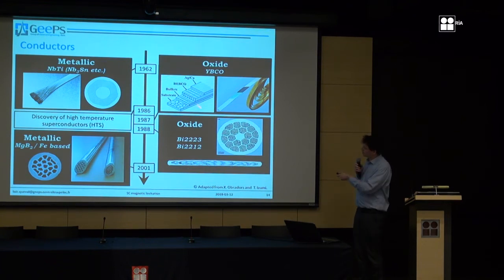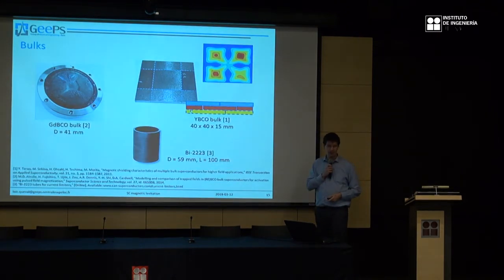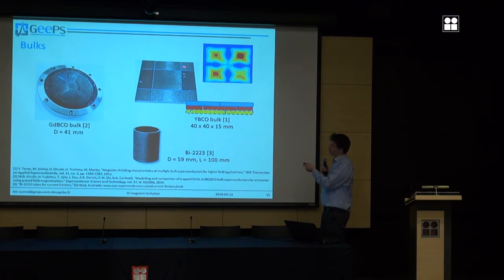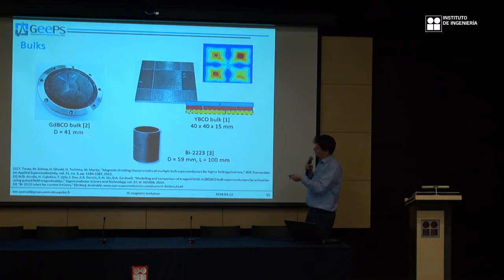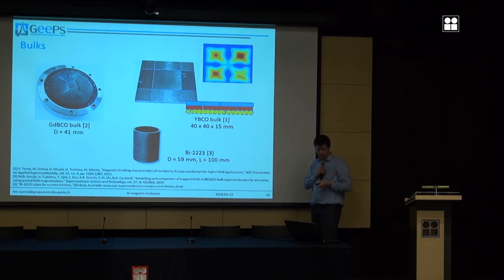The one we saw in the video was this one, YBCO. But not as a tape, but as a bulk. So a bulk is like a permanent magnet, okay? So you can fabricate a tape with your superconductor, or you can fabricate a bulk. You can fabricate a cylinder, you can make plates. For example, here, what we did was to put plates, joined one with the other, to make a bigger superconductor. This is a magnetic shielding, and you can even have strange shapes like these hollow cylinders, okay? And you can use it for your application. All this is YBCO, okay? And this is the one that we are going to use for magnetic levitation, this kind of material as bulks.